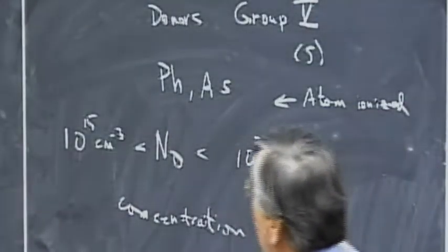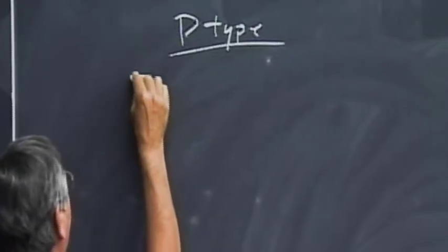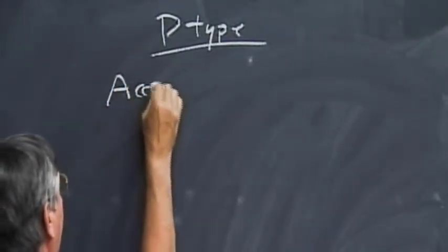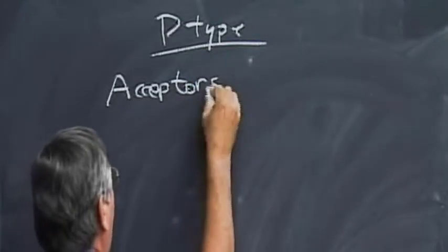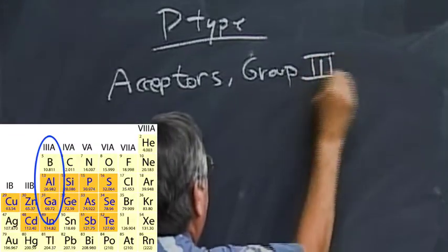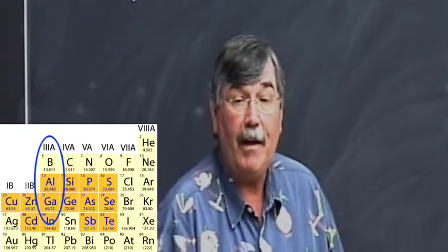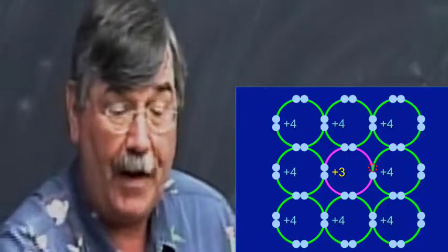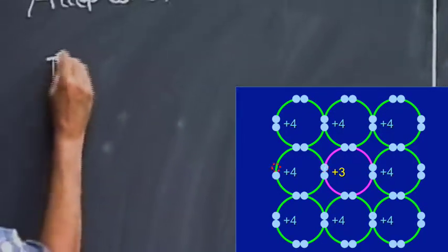Okay? The other side, and I'll go over to board 2 just to illustrate, is P-type material. Same thing. In P-type, we have so-called acceptors, which are a dopant atom, and they come from group 3 of the periodic table. All right, so they have 3 electrons in their outer shell. In this case, we would really like to have 4 valence electrons per atom for bonding purposes, for chemical purposes. And so it is very easy for an electron from somewhere to come and ionize these acceptors.